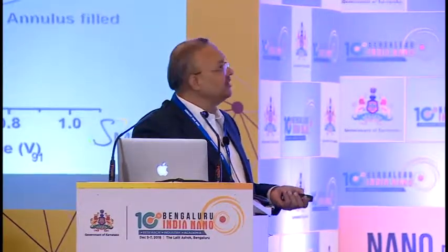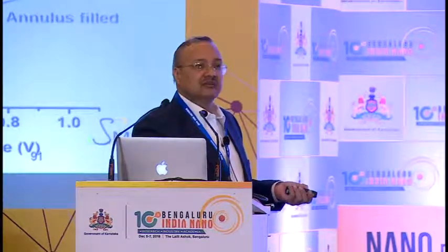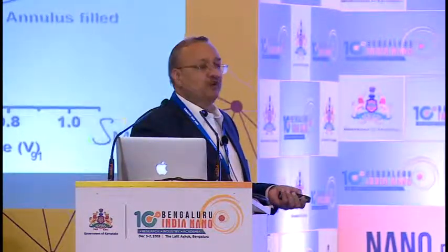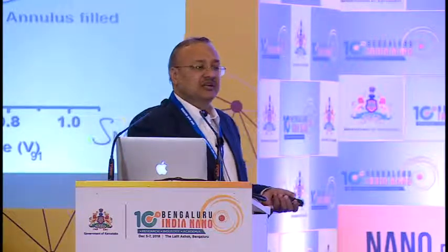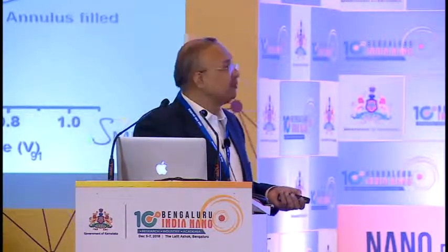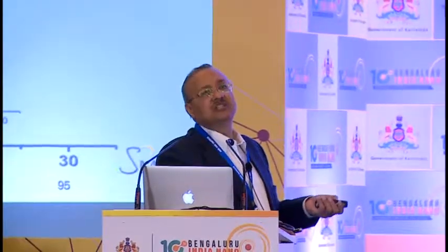So we looked at cyclic voltammetry, and we found it has a very high capacity. And if you filled both core and annulus, the capacity went up many times. Is it flexible? Yes, we did a loop test, and nothing much changed. Then, is it stable? We did a lot of cycling. Yes, it does change. But from 100%, the retention came down to about 70%, and then remains nearly stable. But these are all research devices, so there's no optimization done. They are just made to show a concept.